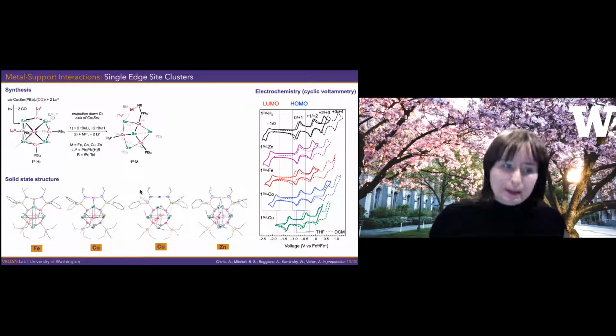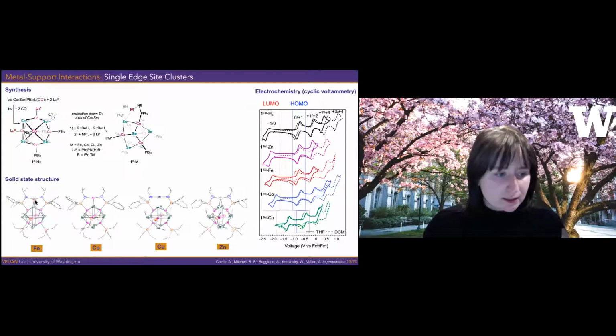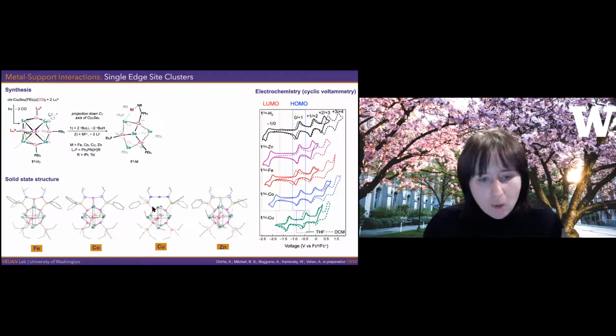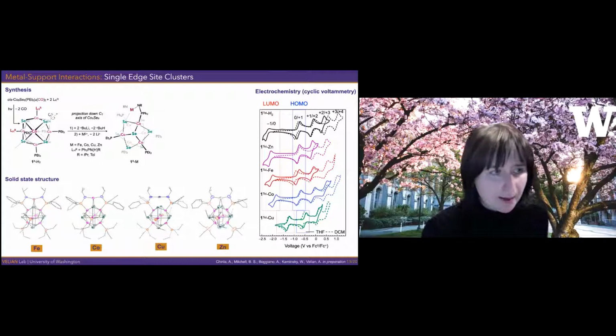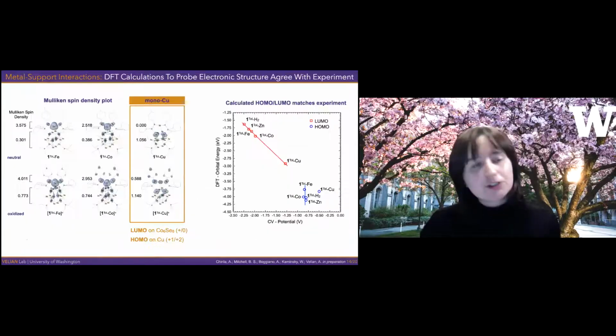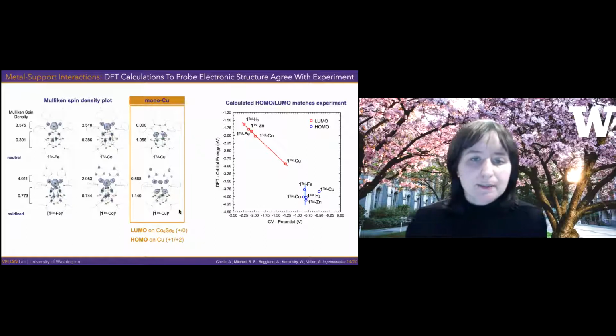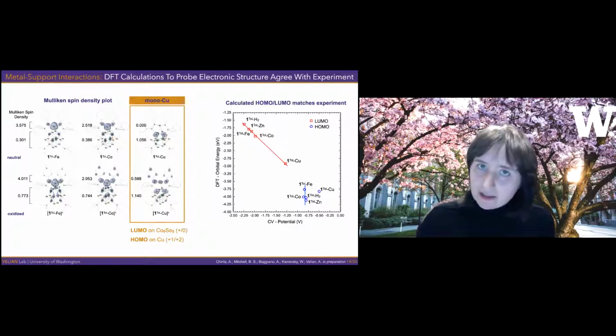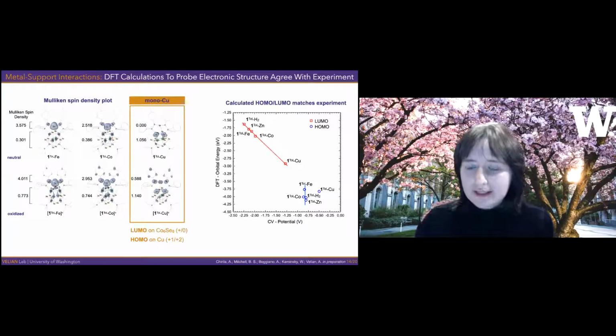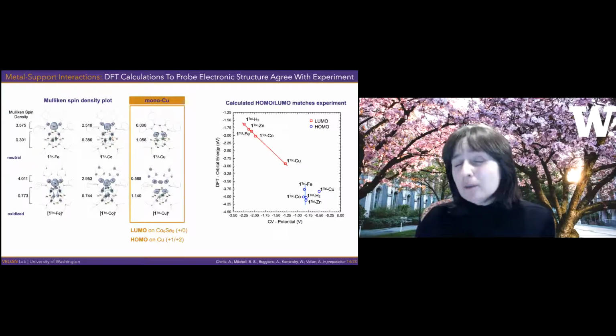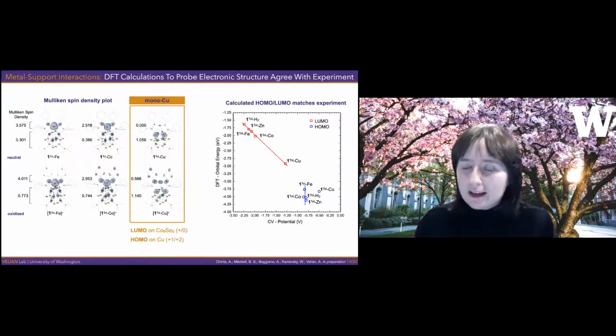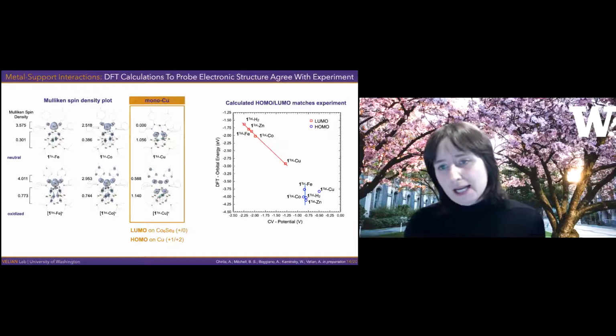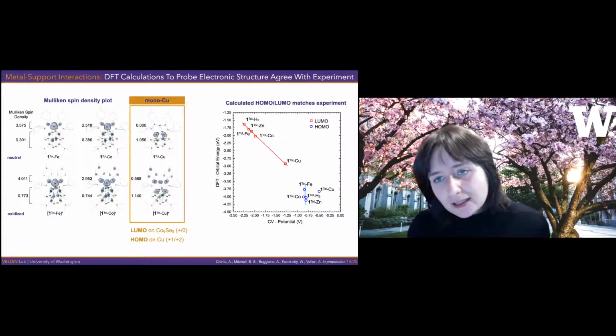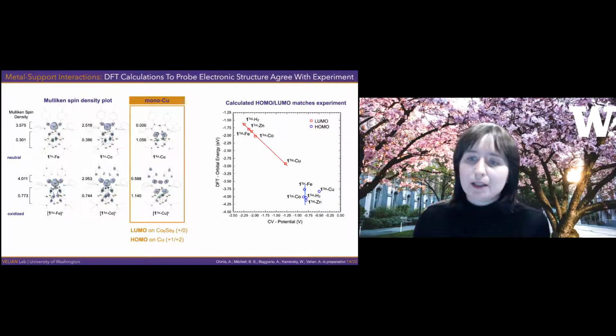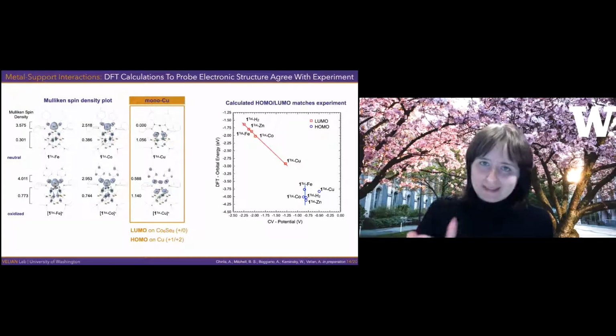So we can use synthetic chemistry to isolate this series. And so here's a single iron on the cluster, a cobalt, a copper, and zinc. And we can use electrochemistry to probe them, same way that we did before. I won't go into all of these details, but the cool thing is that now we can calculate the electronic structure of these clusters. And we actually find that a little bit surprising to us. These are complex systems, a lot of metals there, open shell, many of them. But what we see is that the calculated HOMO-LUMO gap matches fairly well the experimental values, and we see the same trend of the LUMO being stabilized the most.